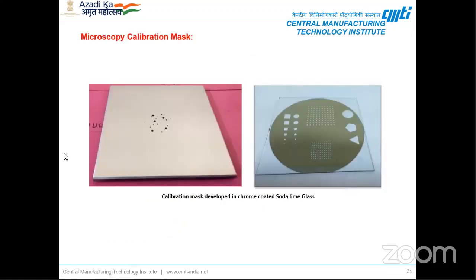Another application is a microscopic calibration mask. These are used to calibrate microscopy equipment. These are also import substitutes. We have fabricated them with the excimer laser. These are chrome coated glass. We have created small features ranging from 1 to 1.5 micron up to the mm range. Here you can also see various features we have created in chrome coated soda lime glass.